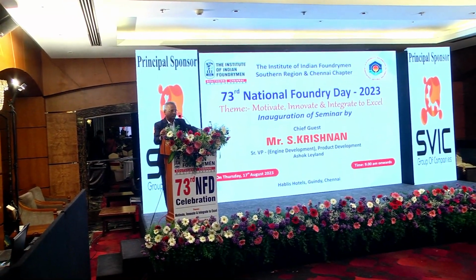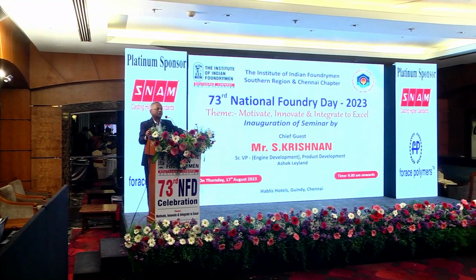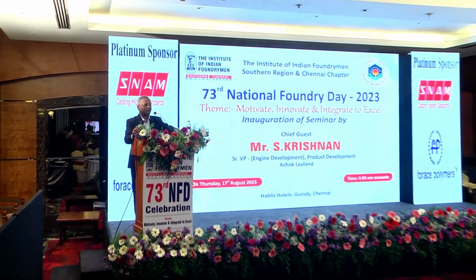No, 144 plus is a coating. It is a mixed refractory coating, basically graphite. Normally for any critical cores, like water jacketed blocks or heads, what you need is a highly insulating coating. A lot of foundry chemical suppliers say they have an anti-veining coating, but I personally don't believe that coating alone can eliminate veining, because the root cause of veining is sand. If you work on sand, there is no need.